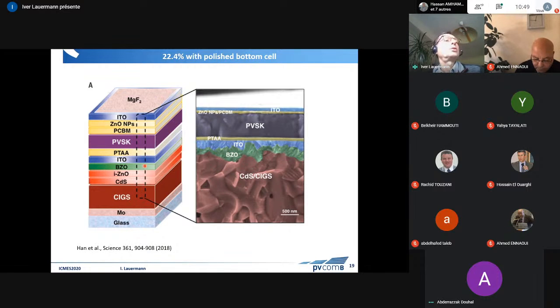This cell was shown in 2018. What they did was, in order to avoid the rough surface of the CIGS, you can see how rough it is, because this gives big problems with the thin perovskite layer on top. They actually polished this part here. They made a very small cell, they polished it, and then put on top the top cell. And they reached 22.4%, so a big jump from the previous.